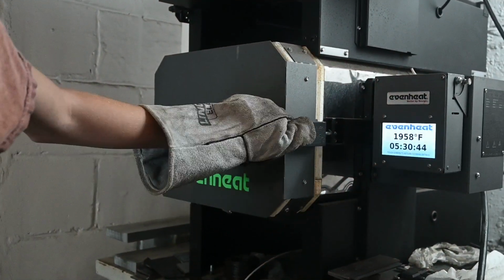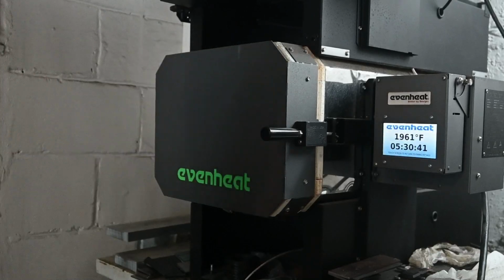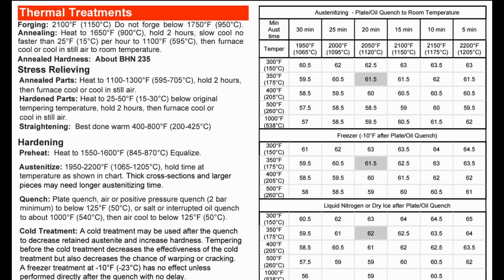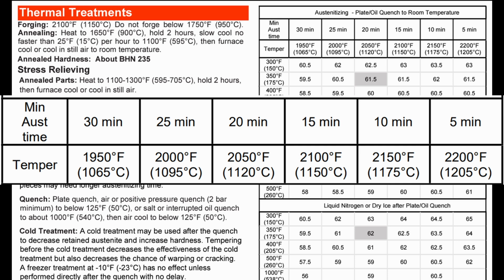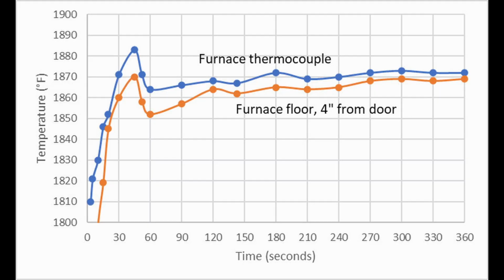It's 2050 degrees. And there are hold times for each temperature. This is for a fixed thickness of around 1/8 inch. You could go for a longer hold time if you have thicker steel. If you have 1/4 inch, you should probably hold longer. So it says for 1950, hold for 30 minutes, 2050, 20 minutes, and 2200, only 5 minutes. The hold time is supposed to be after the steel has reached the target temperature. Sometimes I cheat and I start the timer after the furnace has rebounded back up to the temperature. The temperature of the furnace drops from opening the door and also sticking in a cold piece of steel. And then once it gets back up to temperature, I will start the timer.